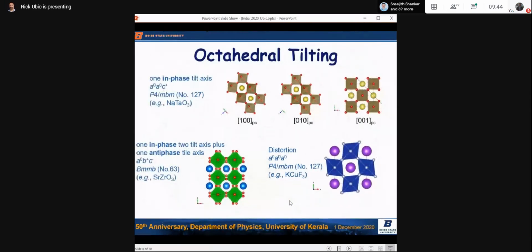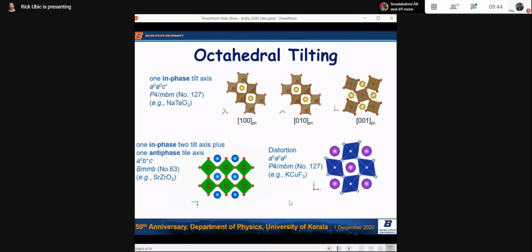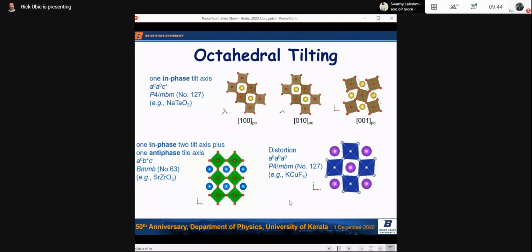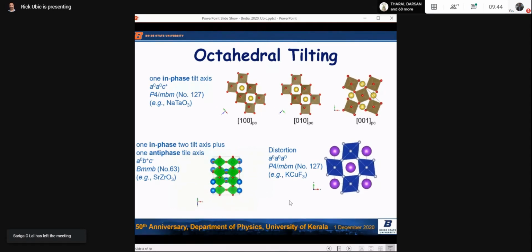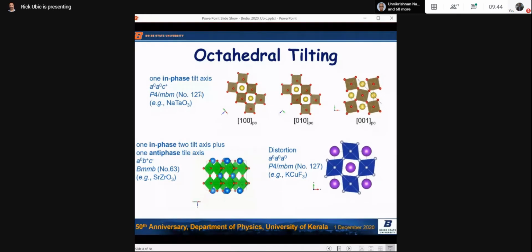So there are lots of other things that can happen with perovskites generally. I won't talk in our modeling a lot about tilting, but just to introduce the subject, perovskites generally exist in non-cubic tilted forms, which means the octahedra tilt like this, or like this, about an axis. They've got 3 pseudocubic axes. They can tilt about any one of those 3. So some specific examples.